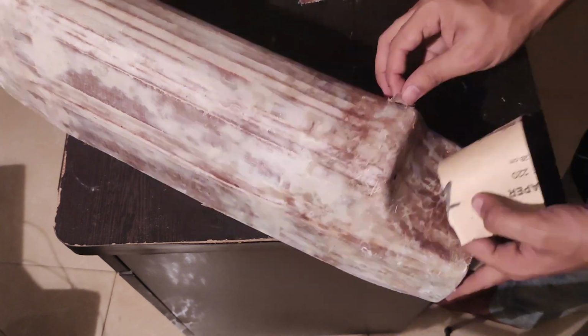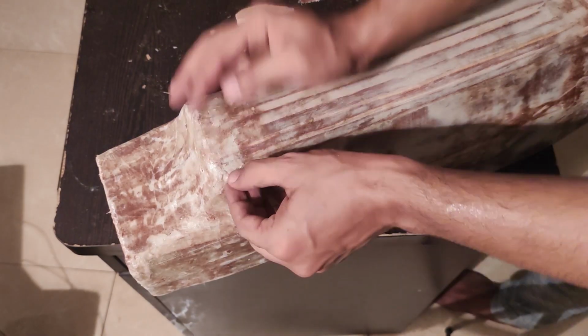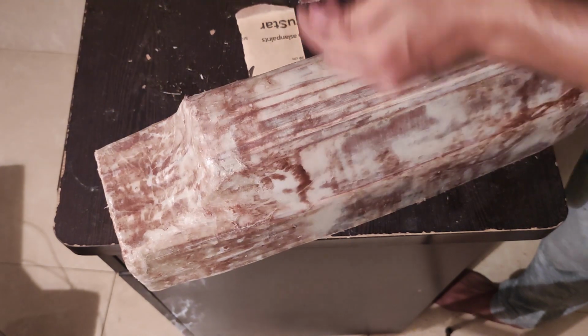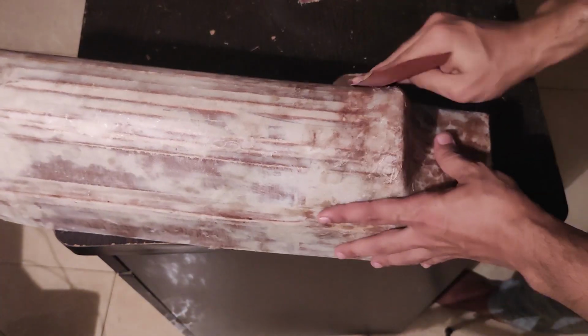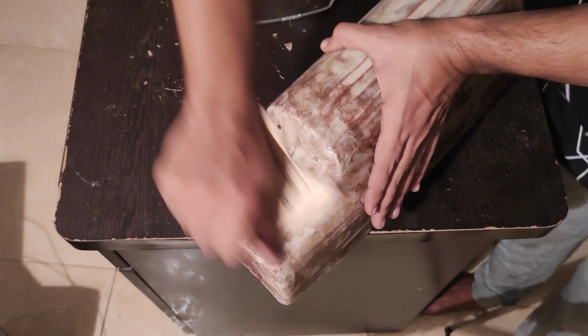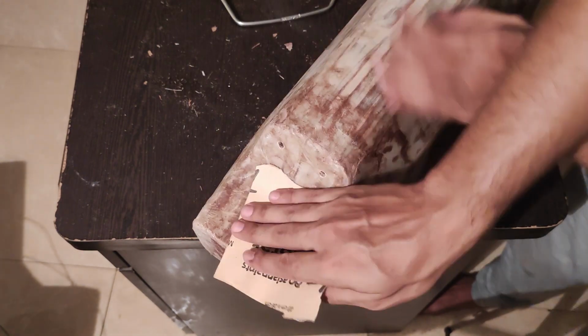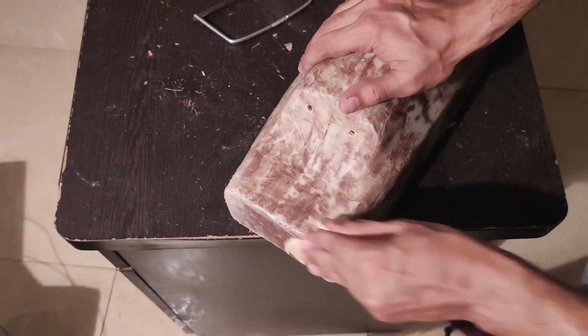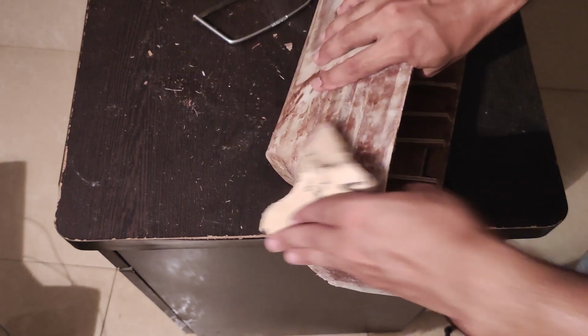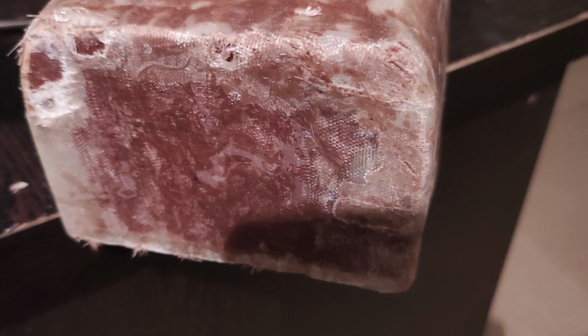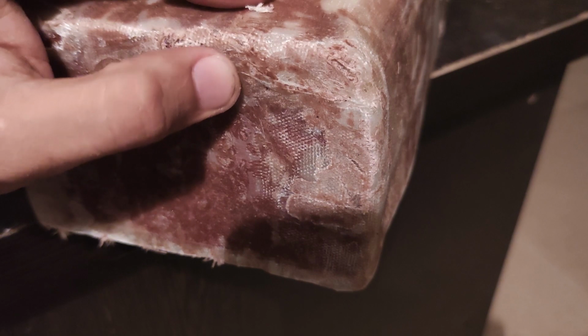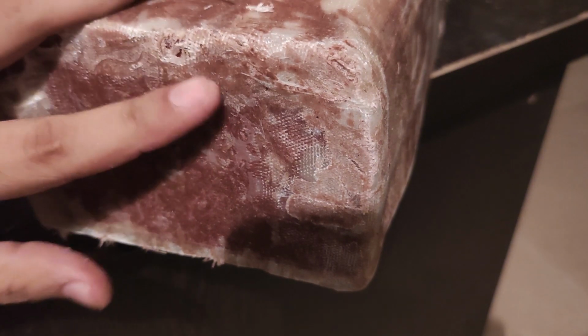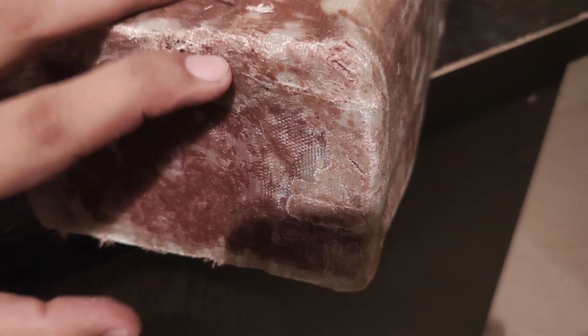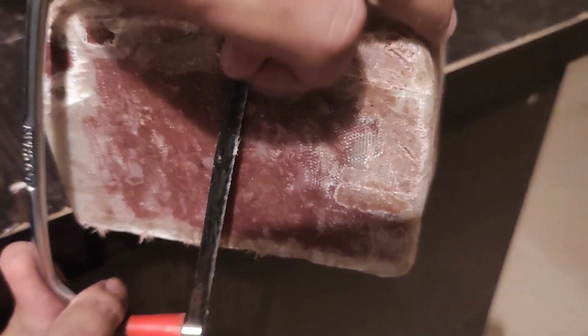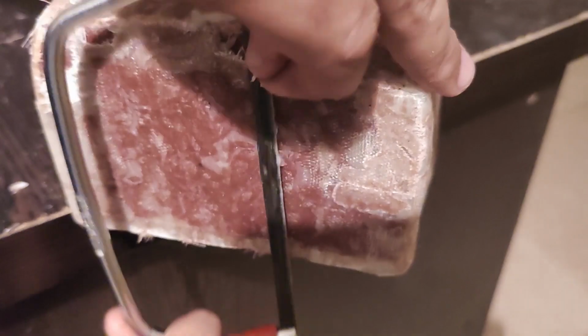You can see those air bubbles causing the fiberglass to rip off. Look at these massive defects formed at the curves. To fix these, I used the saw to rip off the voids and simply used epoxy resin to cover for it. And yeah, it worked.